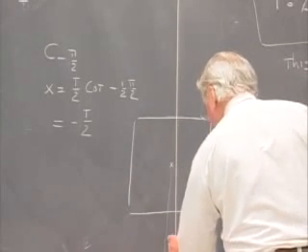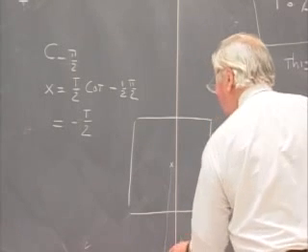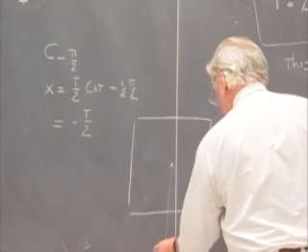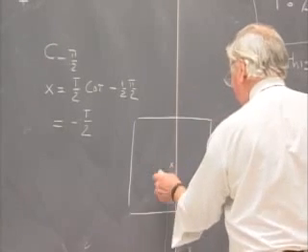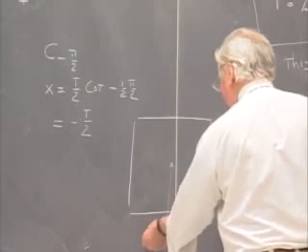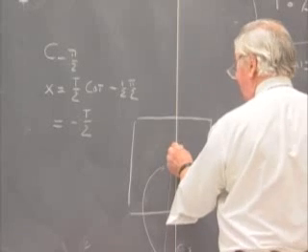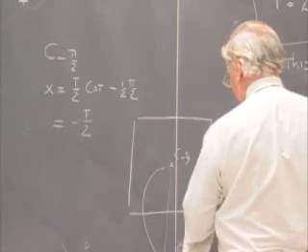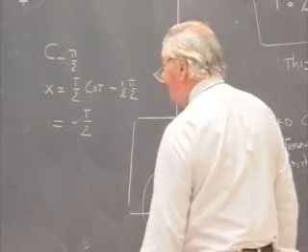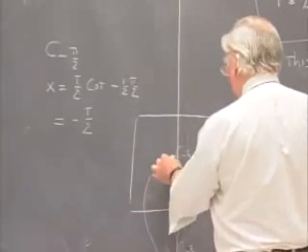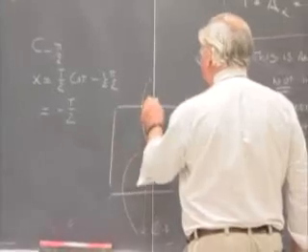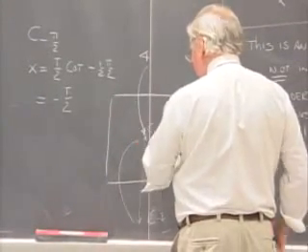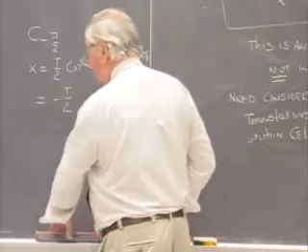And this will be the rotation c minus pi over 2. But everything has to be translational equivalent at the interval t, so I can just move this operation c minus pi over 2 up to the center of my original cell. So now I have at the center of the cell all the operations of a fourfold axis. So a fourfold axis exists in the middle of the cell.